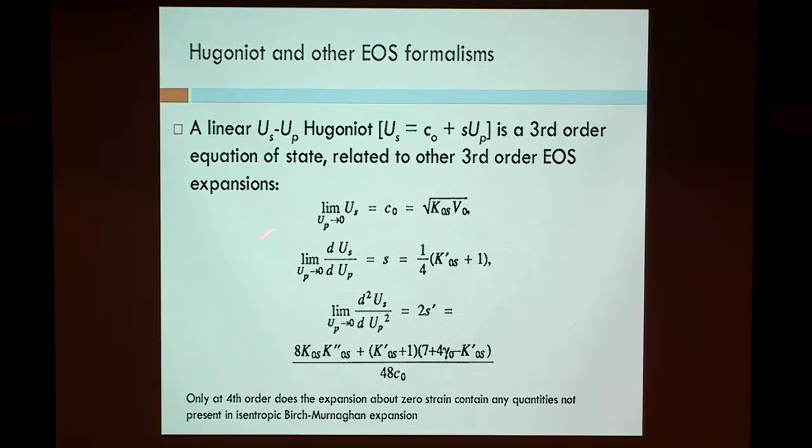Okay. Well, K0S is the isentropic bulk modulus. It's V times dP dV at constant S, right? It describes the pressure change for a unit volume at constant entropy as opposed to K0T, which is the same thing at constant temperature. And there, what he was talking about was K0T when you're fitting the Birch-Murnaghan. Right. So if you're doing isothermal experiments, you're measuring KT, K0T. If you're interested in elastic behavior of materials, because elastic waves are adiabatic changes of state, actually what you want is K sub S. The conversion between them requires some additional information about thermal expansion and heat capacity.